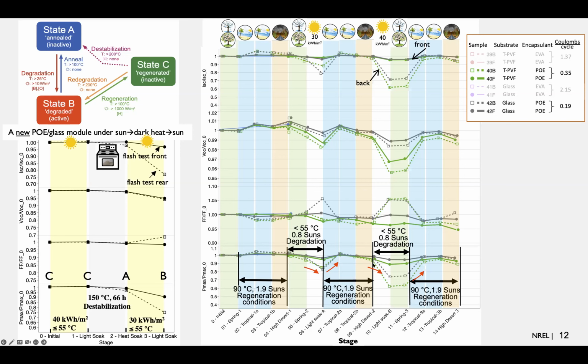So this part is good, and as expected, but unexpected again for the second cycle, when we take it out for a light soak in modest temperatures, basically outdoors, we see an important amount of degradation. And then again, for the second time, when we bring it to high temperature in the tropical, we see recovery, again consistent with moving from state B to state C, where we're getting regeneration with temperature and light.